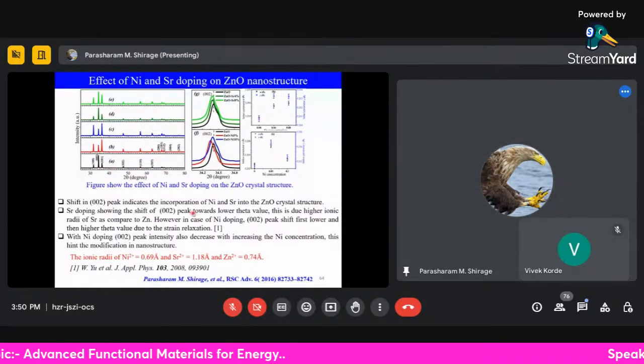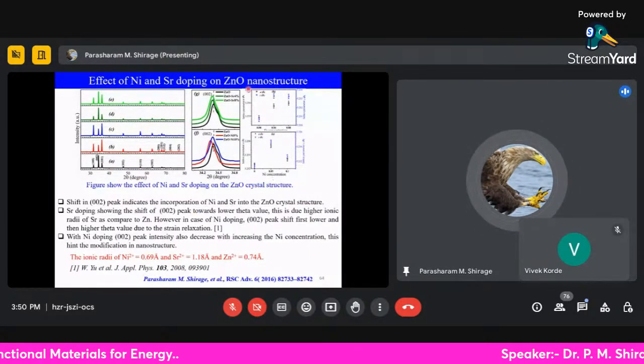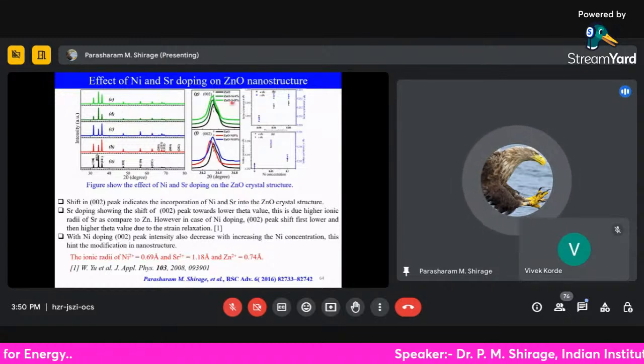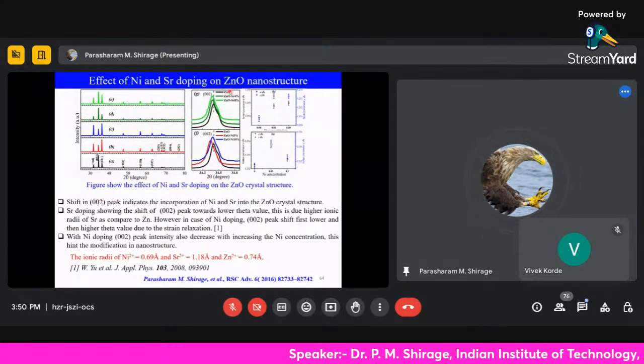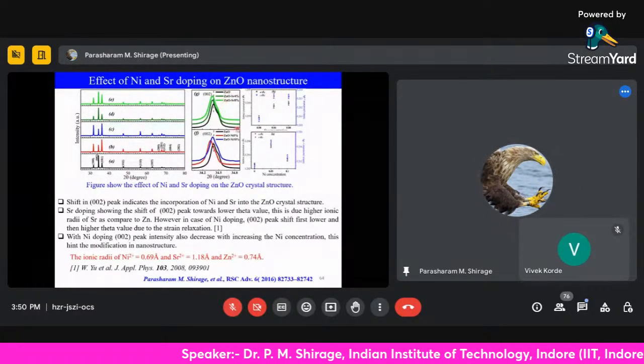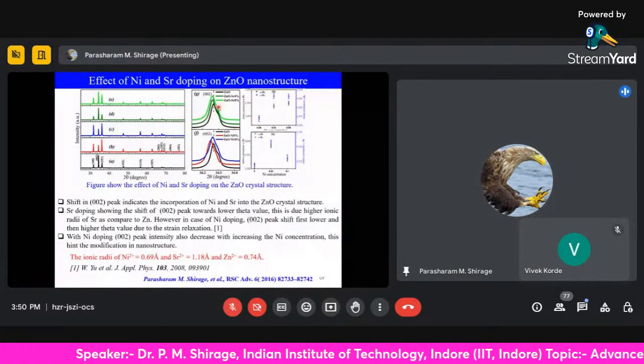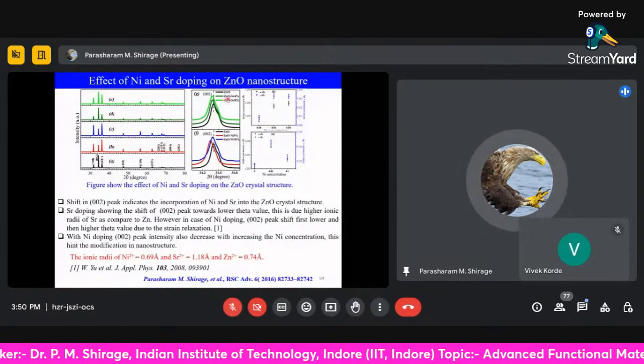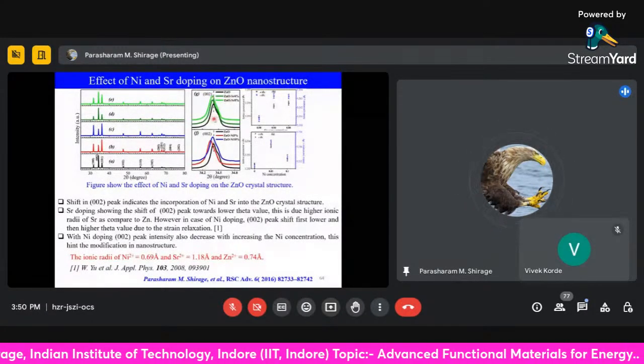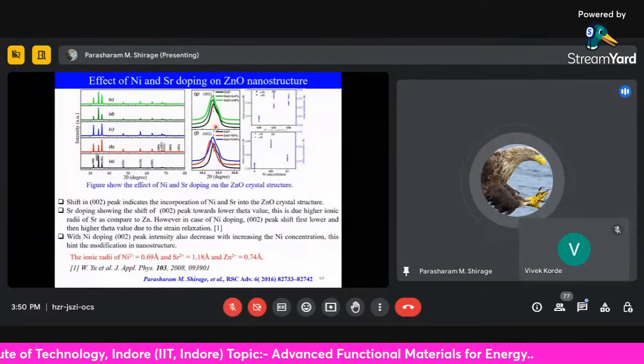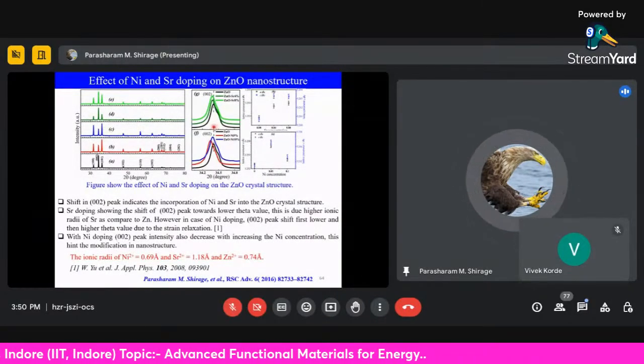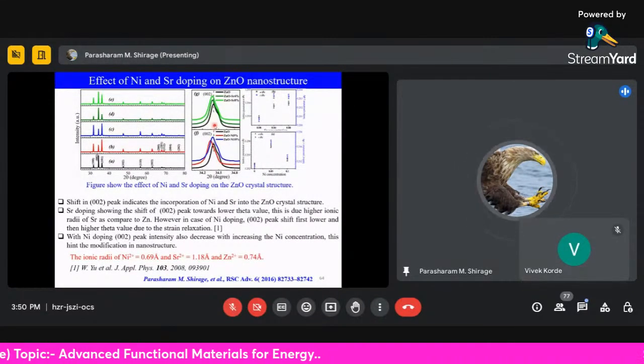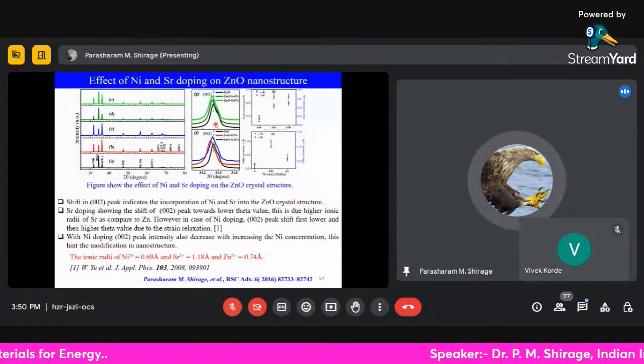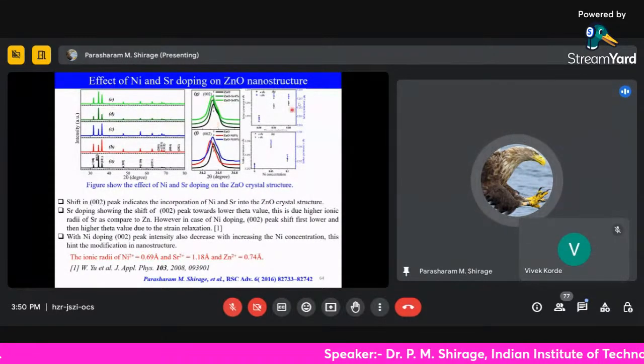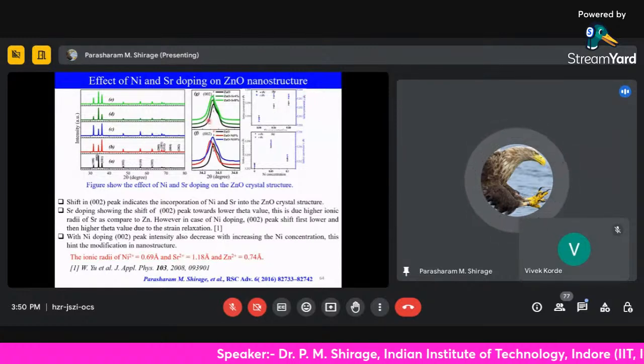Okay. So in case of this strontium doping and nickel doping, you can see this strontium doping. This is black, then this is 4%, this is 8%, this is green. This 2 theta is shifting to lower 2 theta. It means lattice constant is increasing. It means with doping of zinc with strontium, the lattice parameter is increasing. And that is reflected from this XRD.